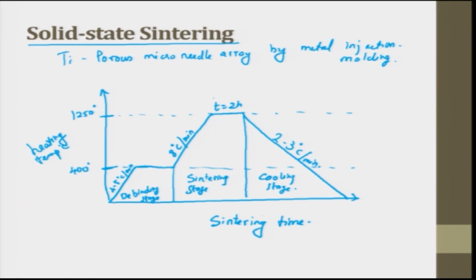If you see here, you can't go straight to 1250 and start the sintering process. You do it step by step, and slowly at every stage you maintain it for some time. This is called soaking time: you soak it for some time, then you ramp it, then you soak it, then you do the cooling stage. So this is a typical cycle.